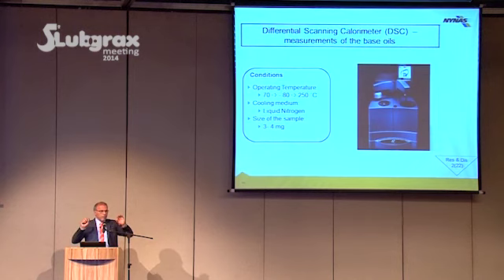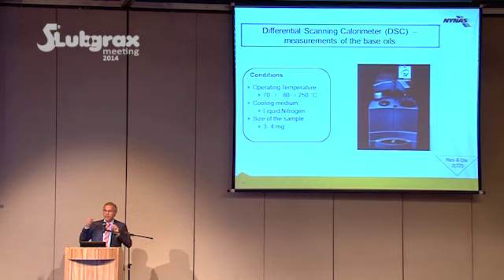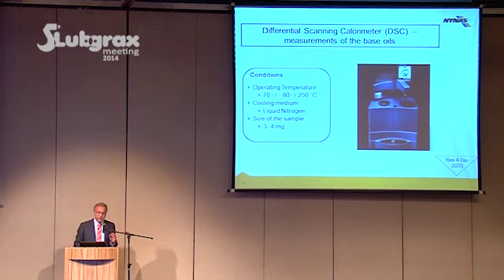So you get the number, but that number doesn't tell you whether that lack of flowability was a result of the high viscosity of the oil or the solidification of the oil. Because if you have wax inside the oil, it will solidify and it will block the pipe. This kind of test reveals what I state here.